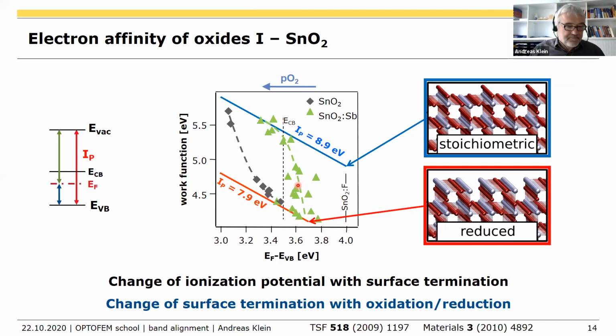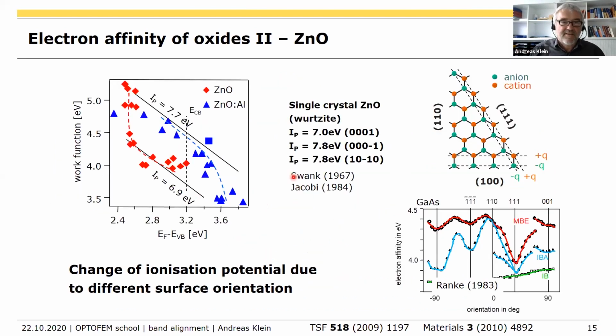Okay, we get similar things for other oxides. You can also look at zinc oxide. So the surface termination is not the only thing. You get a very similar plot for zinc oxide with a low ionization potential of 7 eV and a high ionization potential of near 8 eV. The difference now is the orientation of the films. So if you are more reducing, you usually have a 1-1-1 surface orientation. And if you go to more oxidizing conditions, it partially turns around and you get an anion terminated surface.